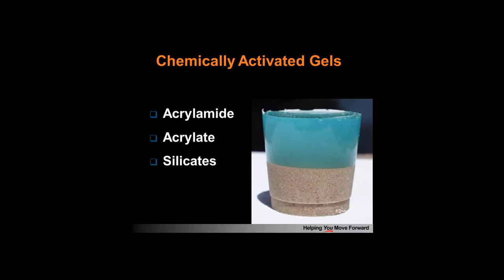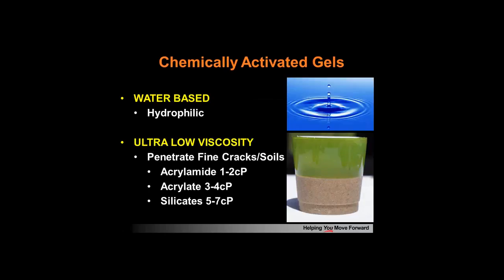Moving on to chemically activated gels. Within that family are acrylamides, acrylics, and silicates. Chemically activated gels are water-based, making them hydrophilic in nature. They often have ultra-low viscosities with the ability to penetrate very fine cracks in soils. Acrylamide has a viscosity of 1 to 2 centipoise, acrylics is 3 to 4 centipoise, and silicates 5 to 7 centipoise.